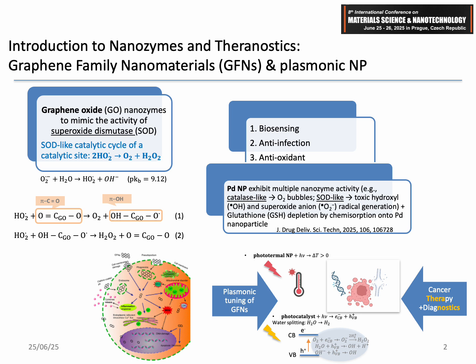To note, the palladium nanoparticles also exhibit strong catalytic behavior and can combine multiple nanozyme functions, including the catalase-like activity, producing oxygen bubbles which affect the cellular mobility, the SOD-like activity that we have already described, and the glutathione depletion via surface chemisorption. And when integrated with plasmonic nanoparticles, the graphene can enhance their photothermal and photocatalytic properties, which paves the way for advanced theranostic platforms that unify all these multiple functionalities.